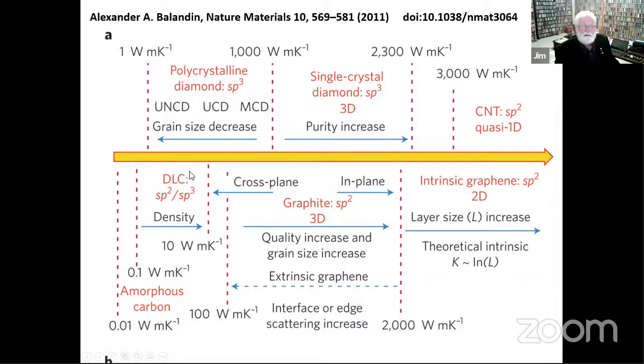Diamond-like carbon surprised me because I thought when this was all the rage that it was supposed to be a high property, but not as good as graphite. Polycrystalline diamond, better than diamond-like carbon. Single crystal diamond, this is industrially made diamond. This is gemstone diamond. If you want to go to your friendly neighborhood jeweler and buy your heat sink in the form of gem quality diamond, this is where you are. But carbon nanotubes are way better, and graphene is potentially better still. So the interest here is in two-dimensional graphene. Carbon nanotubes are basically one-dimensional, graphene sheets two-dimensional.